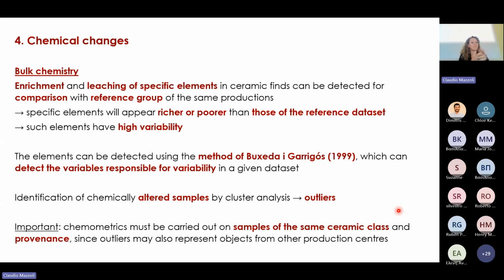But it's not always simple to do that, right? So we thought about how to face this problem and what to do. The best, as I said, is to take a reference collection and make the comparison. A way to do that is to consider the chemical composition of your ceramic and to try to define which are the chemical elements which varied using a method like the one proposed by Buxeda i Garrigós in 1999, in which you can study the variability of each chemical element in the complex of the data set you are analyzing. Okay? It's quite complex, but you can take a matrix of these elements and see which are the elements much more variable inside the data set.